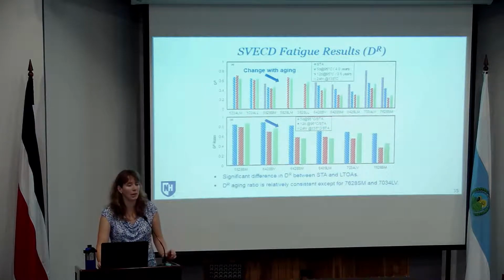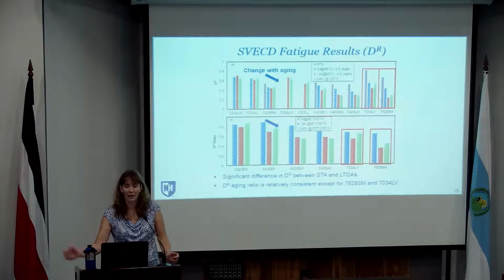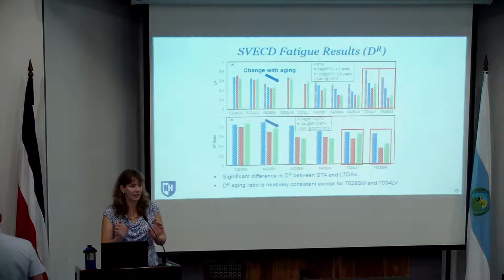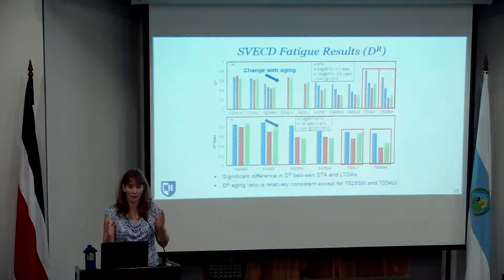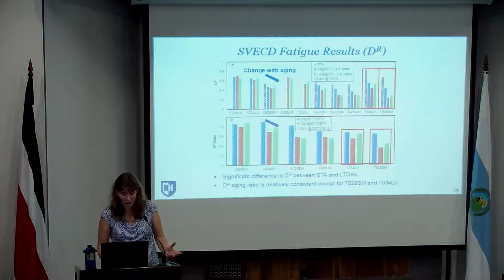The other thing that we started to notice was that for a lot of the mixtures with the typical New Hampshire binders, so those PG 58s, 52s, minus 28, minus 34s, we're seeing similar ratios. But then when we looked at those two specialty materials, the highly polymer modified materials, the 7034 and the 76 minus 28, we're seeing a difference in behavior. So it seems like these tests or these evaluations were able to separate more traditional binders from those polymer modified binders. And one thing with the polymer modified binders, and you'll see this in some of the other results, they do